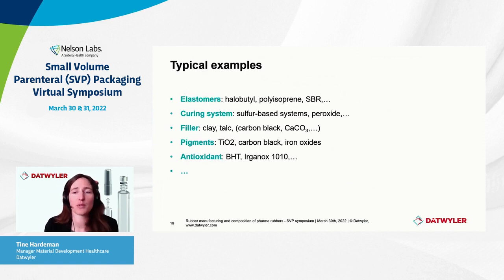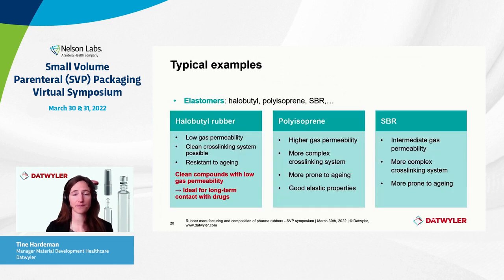Just to give you a bit more a concrete idea of what this means, I gave some typical examples. First, for the elastomer, and this is, of course, really a very important choice because this elastomer is the backbone of your rubber. I gave some more details here. So for the pharma segment, halobutyl is really very much preferred. You can also find some polyisoprene and SBR, and those are actually more or less it. There is some nitrile rubber for very specific applications, but these are by far the most popular ones. This is a bit different from the general rubber industry, where, for example, EPDM, etc., is very popular.